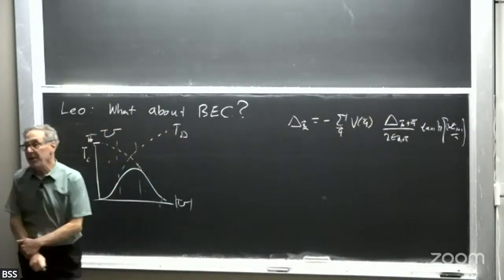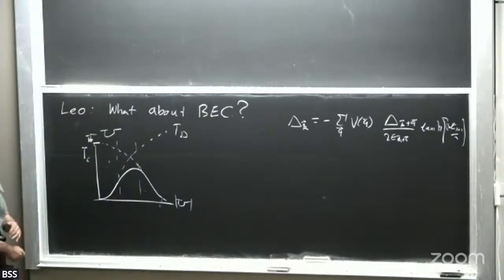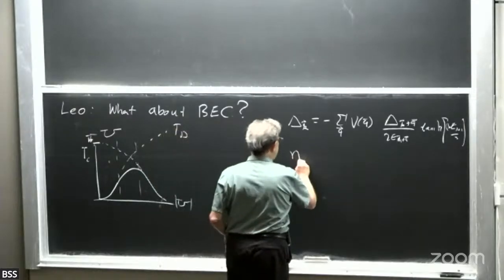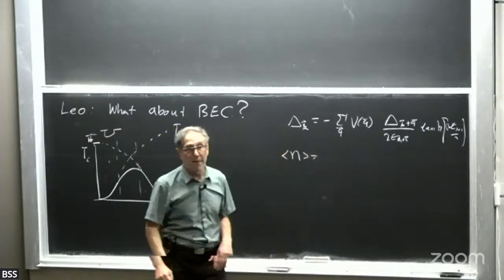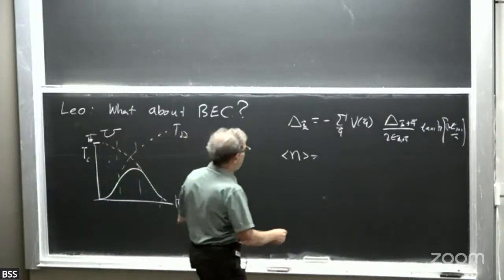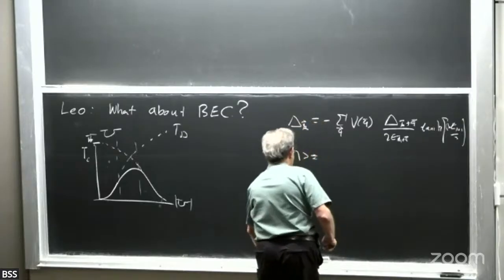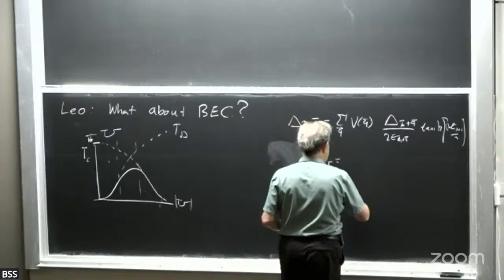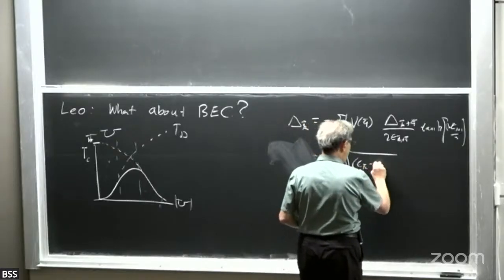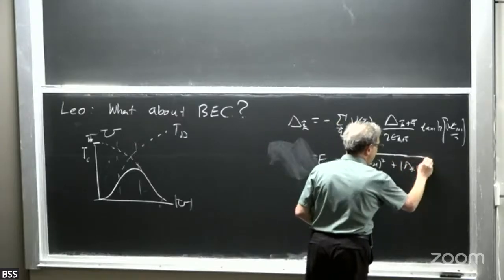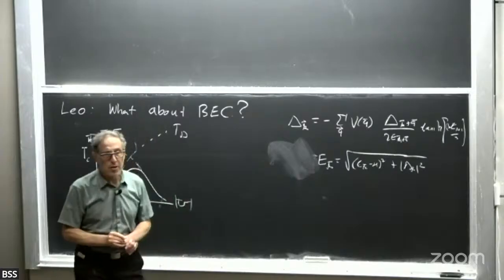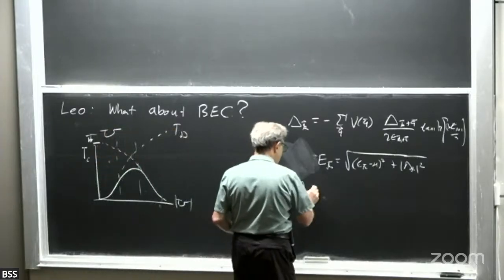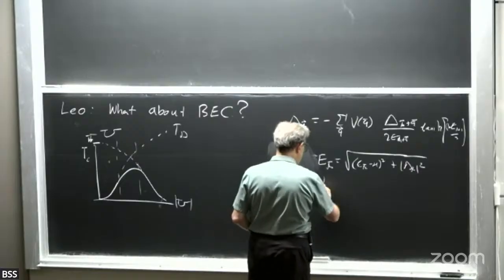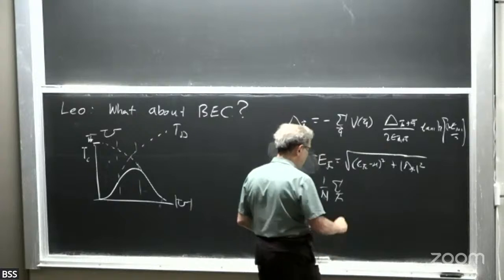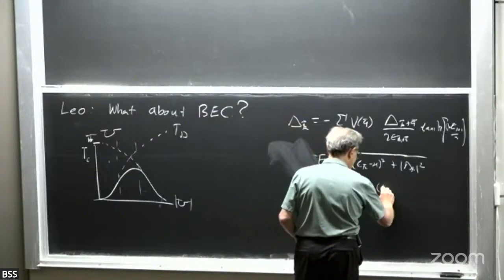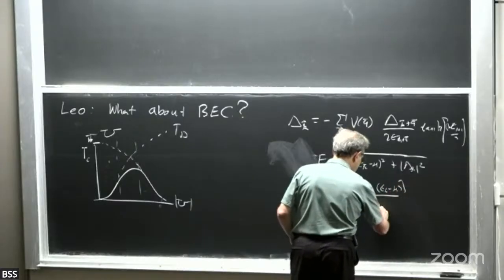But there's another self-consistent equation that's usually neglected because it's not important, which is that the expectation value of density doesn't change. Oh, sorry, I have to say what E_k is. E_k is equal to the square root of (epsilon_k minus mu) squared plus delta_k squared. And mu is the chemical potential that has to be determined self-consistently, from the equation n equals 1 over N sum over k of (E_k minus (epsilon_k minus mu)) over 2E_k.